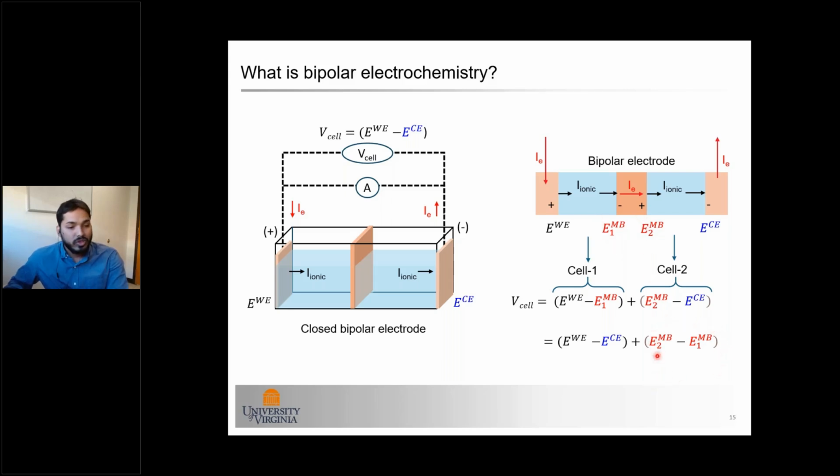And the offset, if you compare it with the conventional setup, depends on how much current you are flowing through this circuit, and of course the electrolyte on each side. If you have the same electrolyte and if the current is negligible, your offset is also negligible. Both surfaces are at their corrosion potential or open circuit potential.